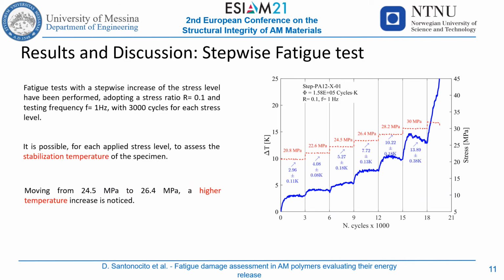Fatigue tests with a stepwise increase of the applied stress level have been performed on 3 specimens with a stress ratio of 0.1 and 1 Hz of frequency. During the test, the superficial temperature has been monitored with the infrared camera. For each stress level, it is possible to observe and estimate a stabilization temperature. For the last stress level, no stabilization has been reached and the temperature increased until the specimen's failure. Moving from 24.5 MPa to 26.4 MPa, a higher temperature increase is noticed, hence the fatigue limit of the material falls within this range.